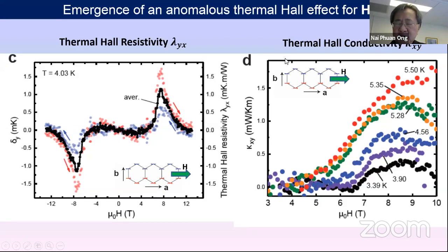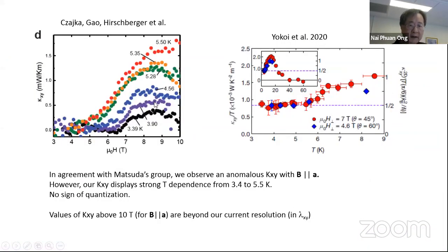No thermal Hall signal when the field is parallel to the armchair. There is a thermal Hall signal in the quantum spin liquid regime when it's parallel to zigzag. Unfortunately, we do not see quantization. So here I repeat the data. We have checked our measurements against theirs. See, the data again stops a shade below 4 Kelvin. We are going down to 0.3, which will be way over here. And we're seeing that the signal systematically increases and then sails right through this quantization line. So if it's there, we could have missed it. We are currently improving the measurement to see whether we've missed the quantization.